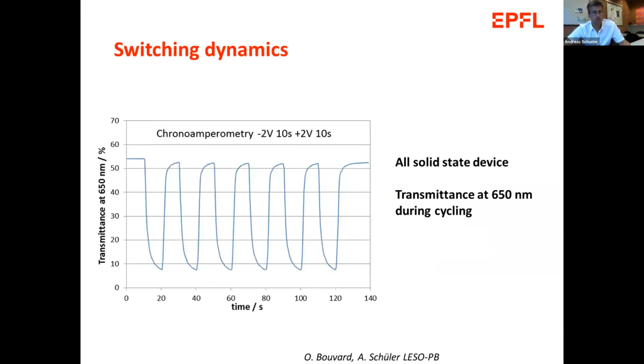The switching speed is also important, to the order of 10 seconds. So here we measure the transmittance at one wavelength, 650 nanometers, and we would measure the transition time. And this is really in this time scale. And this is very important also for the application in buildings. The window should switch on the second time scale ideally.